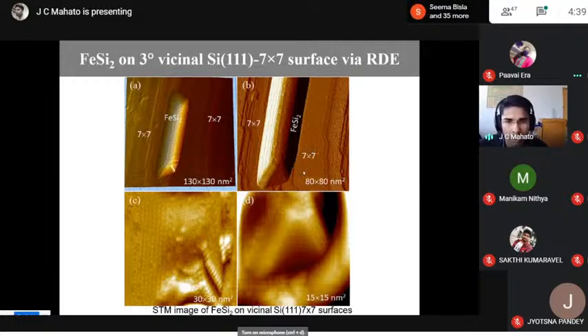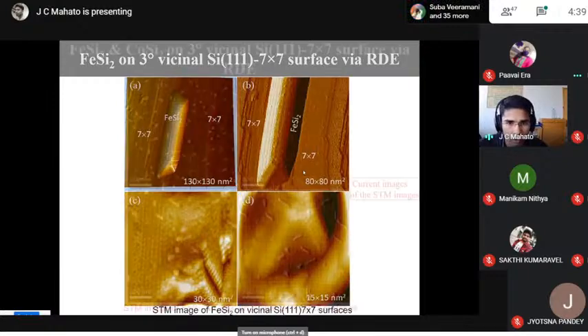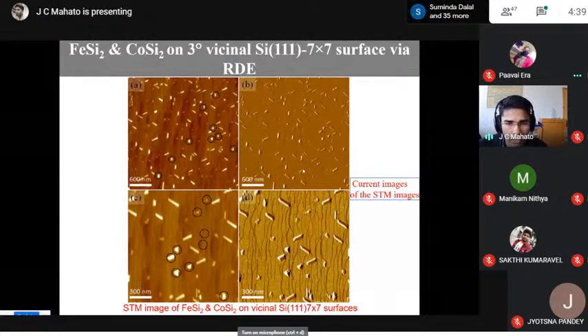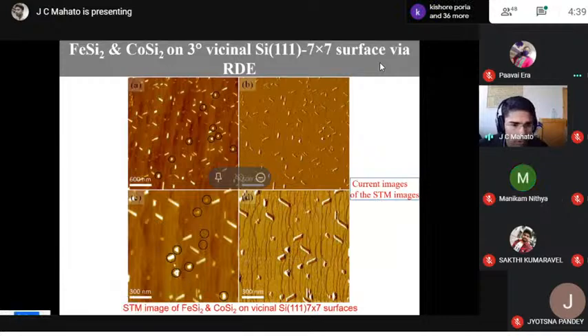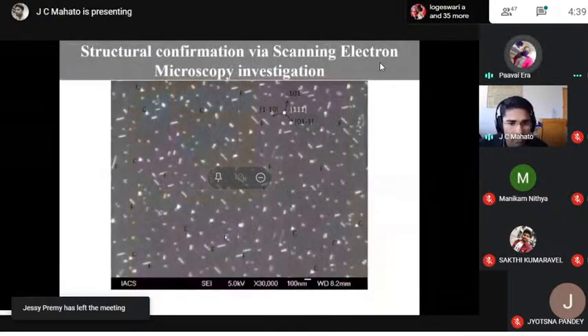For that, we brought back this iron silicide template surface to the growth chamber and deposited cobalt at 600 degrees Celsius. And cobalt also reacts with the silicon surface. The metal silicide is actually very reactive with the silicon, and it forms a silicide. So we can see new triangular and a few trapezoidal type nanostructures that have been grown from the STM investigation. These are the newly grown cobalt disilicide nanostructures, which were absent before.